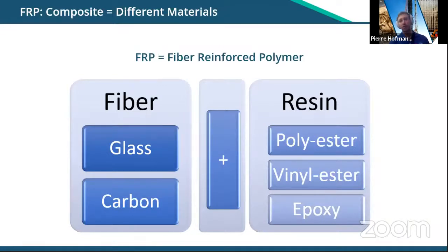The fiber would probably give most of the mechanical performance, while the resin on the other side is really what will give the durability of the product. So typically we use polyester for the temporary application. So again, we mentioned soft tie, tunneling, we'll use polyester because it has a shorter lifetime. When we look at permanent application, we will have to upgrade to other type of resin, typically vinyl ester or epoxy.